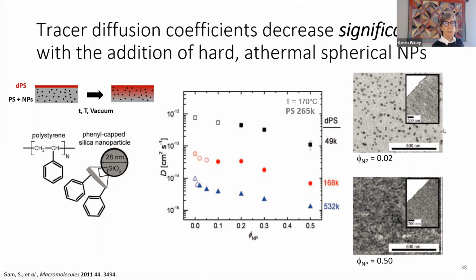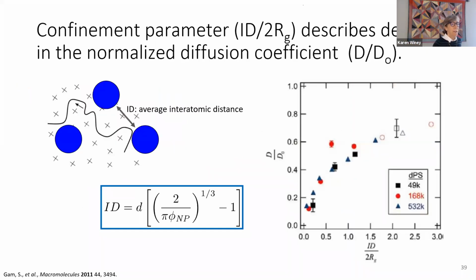Right. And this is just highlighting that we have a processing trick that allows us to get well-dispersed particles. Even though these are athermal particles, and thermodynamically, they want to find one another and stick. But kinetically, we've kept them apart. And so this was the first time we collapsed data. This is the normalized diffusion coefficient as a function of the interparticle distance normalized by 2RG.